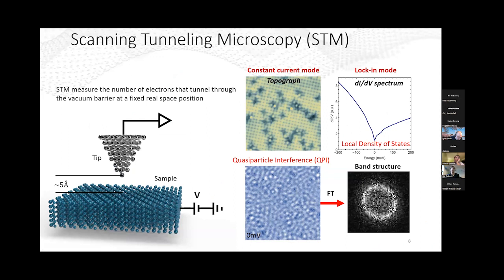So we wanted to probe this kind of physics using STM. What is STM? It is a very simple technique that essentially consists of a tip and a sample. You bring the tip very close to the sample of interest, and then you can measure what we call a topography. That tells us a little bit about the atomic structure of the system. You can measure the dI/dV spectrum that tells us about the local density of states. And what's going to be relevant for today's talk is this specialized measurement that we call quasi-particle interference imaging, which essentially relies on elastic scattering of electrons and their interference from defects in a material. You can see that in the differential conductance or dI/dV maps that I'm showing here. In real space, it looks like waves. If you take a Fourier transform, you can see the prominent wave vectors.